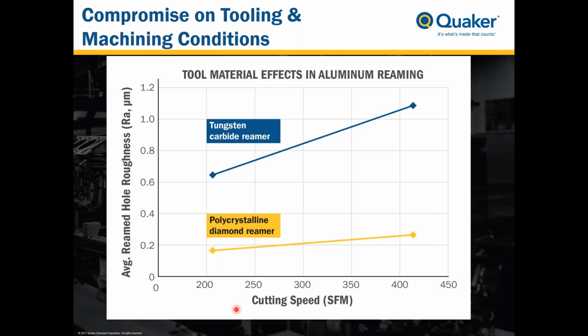Looking first at the diamond tool, what you can see is that at the lower cutting speed, we got very good reamed hole finish, down below 0.2 micron Ra. And then as you go to a much higher cutting speed, it still maintained a very good reamed hole surface finish. Conversely, in going to a carbide cutting tool, you can see at the lower cutting speed, it's considerably rougher, and it's much more sensitive to an increase in cutting speed. So again, it's not a bimetal operation, but it really highlights and demonstrates the impact of the tool materials and the differences between a PCD reamer and a tungsten carbide reamer.